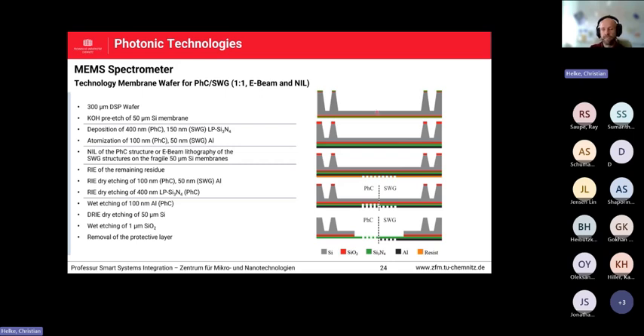Then we deposited the material we need, a silicon nitride layer, which acts as the membrane material itself, and some aluminum, which on the left side acts as a hard mask for etching, and on the right side, for the sub-wavelength gratings, acts as the actual reflector material. Then we performed the nanopatterning on the side with the membrane. For the photonic crystals, we used nanoimprint lithography, and for the sub-wavelength gratings, we used our own e-beam tool.